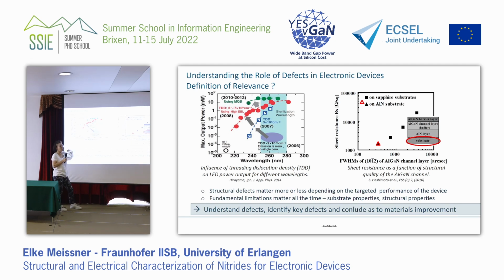If we say we want a deep UV device and we have to emit at 220 nanometers or smaller wavelengths, then any dislocation counts. We want to have really low dislocation density, because any little dislocation will be deleterious. We need the most perfect crystal in order to get any output in this direction. So relevance is a matter of definition, and this is always what you have to keep in mind.